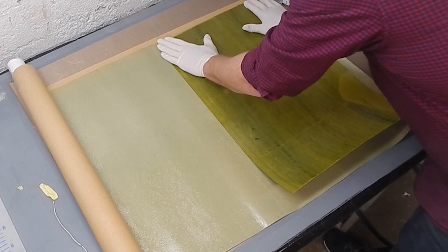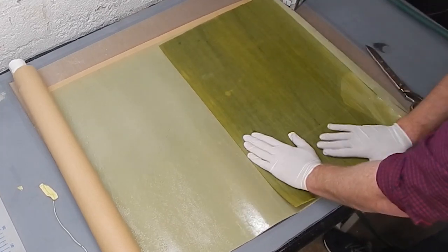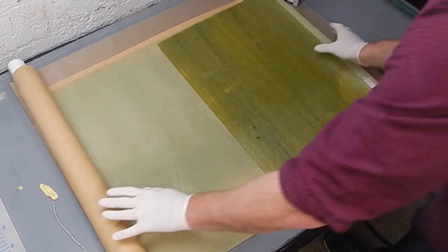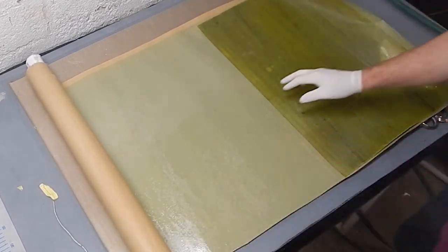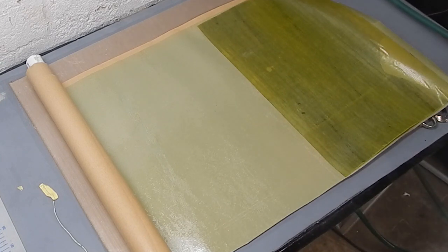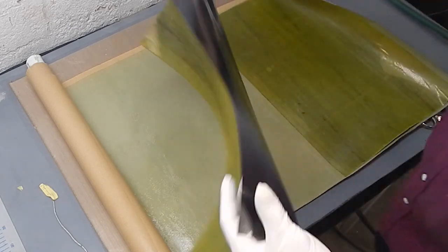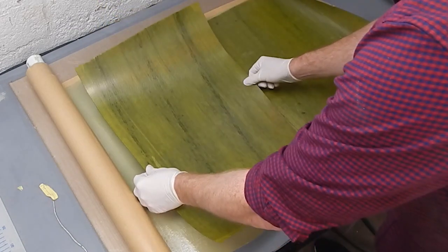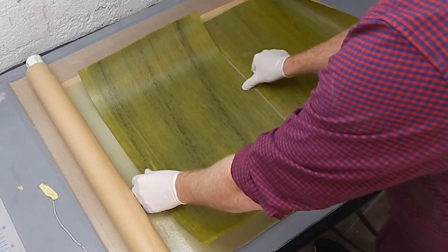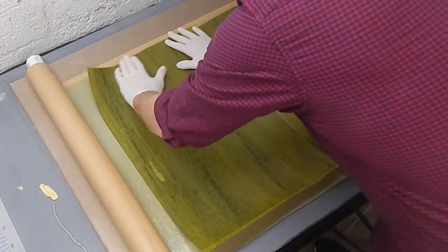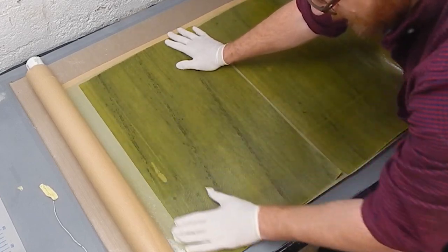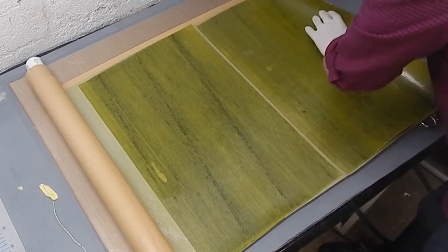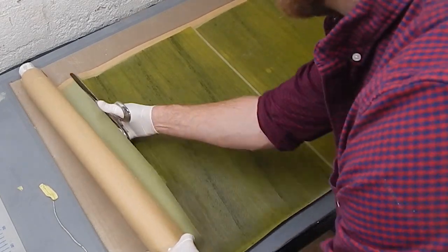So I've done this before in some of the other videos, but I'm just sticking the carbon down directly onto the glue film, removing the paper backer side first, and then I'm going to cut them out neatly so there's no glue film exposed to get stuck to the vacuum bag, and run the spiky wheel over the plastic backer on the prepreg just to help the air get out.